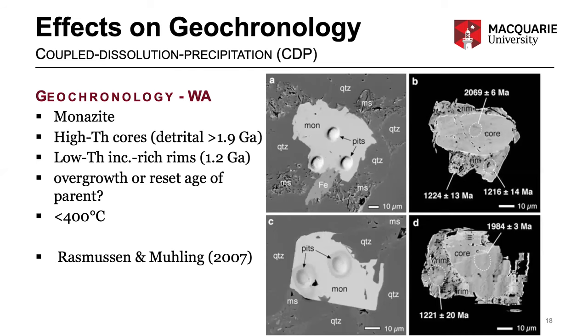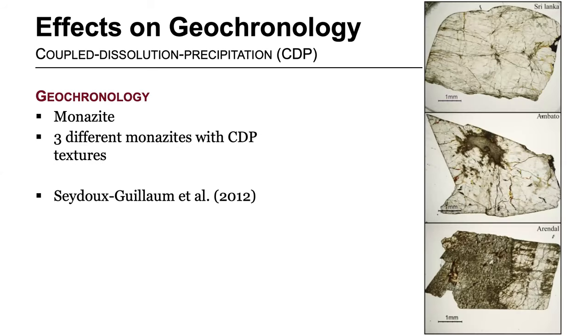So to run through a few quick examples from the literature, here's a low temperature example from WA, where the rims are uniformly 1.2 Ga, and it appears that in this case study, they were reset during the low temperature metamorphism. In this interesting paper from 2012, they looked at pegmatitic monazite in three different locations.